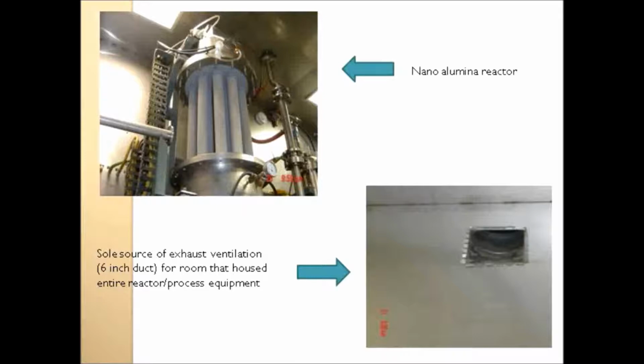So you can kind of do a little quick and dirty math in your head and say, gee, that's an awful small duct to handle a huge volume of air like that. And obviously workers like to really do a good job, and his job was to look inside that reactor, scrape and brush off any residual, and his breathing zone sample was showing this amount of material on the TEM. These are all nano alumina. So you can see that that smaller duct really didn't do much to protect his breathing zone, or for that matter, the entire atmosphere inside of this walk-in chamber, which was about 10 foot square with an 8 foot high ceiling.